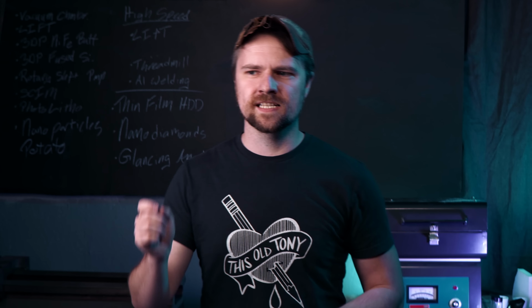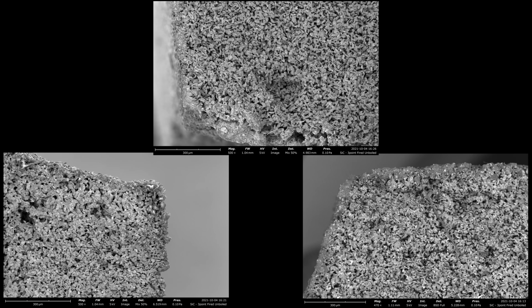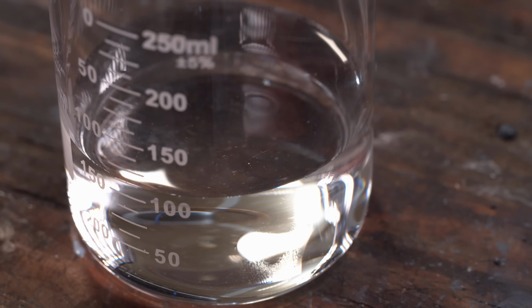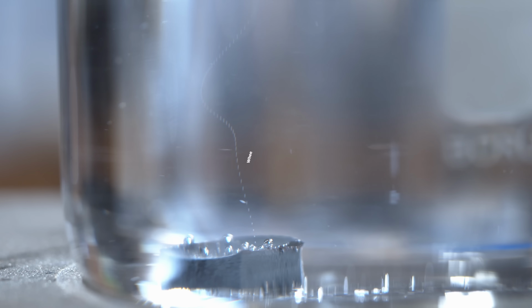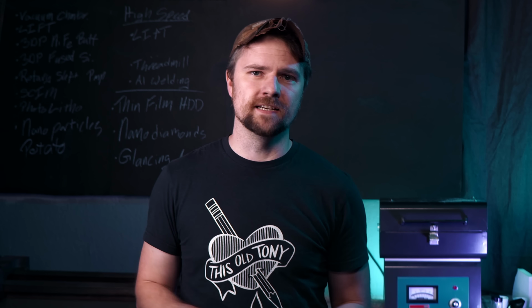But ultimately, I decided to take the sample from the 3-point compression test and break off a piece, image a known section of it to see kind of what the morphology looked like, and then drop it into some boiling water and then re-image. The idea is that if this is just borax that's holding everything in place, it should be soluble in water and it'll dissolve the piece immediately.